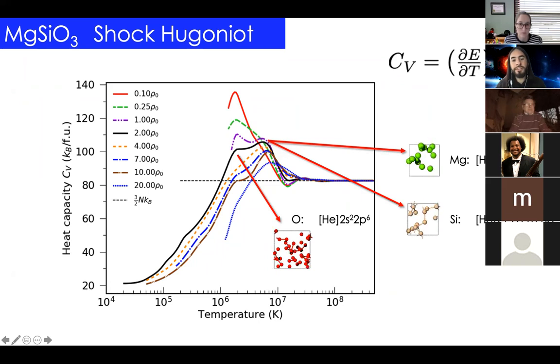For example, this peak here means that the oxygen atoms in the innermost electron shell, the 1s electron shell, are being ionized by temperature at this 1,000,000 kelvins, while the second peak here for MgSiO3 corresponds to the ionization of the innermost electron shells of magnesium and silicon. And if you increase the temperature even more, then you come to a limit where you just have an ideal gas of positive nuclei and negative electrons all going around in a fully ionized plasma. So it's very nice to see how the thermodynamic properties evolve as a function of temperature.